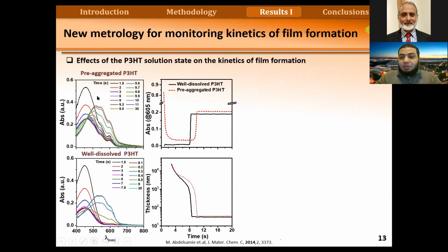We started with two different states in solution. One of them is pre-aggregated, and one of them is well dissolved. We obtained this by using a marginal solvent. This marginal solvent can affect the aggregation of P3HT. If we store it for days without stirring, we can have some pre-aggregation. But if we heat it and continue stirring the solution, we can get a well-dissolved state.